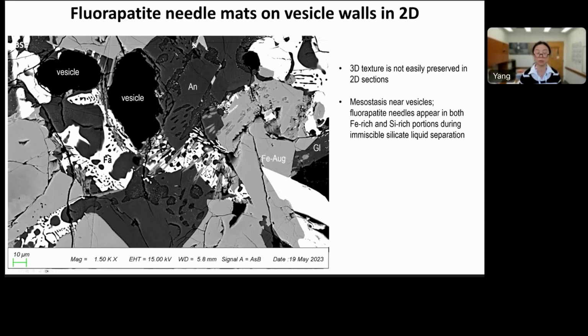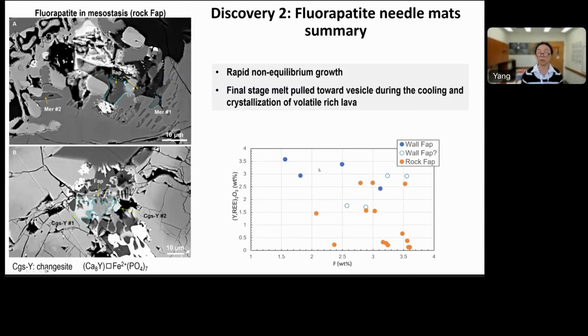They probably do not occur at the same time, but in different melt, probably quickly. So we also compared the chemistry of the needles with fluoroapatite that are in the matrix, but away from the vesicles. We do see this kind of evolution trend in terms of dropping fluorine, but higher total rare earth element and yttrium content. It's suggesting the melt they grow out of is much more evolved, more fractionated.